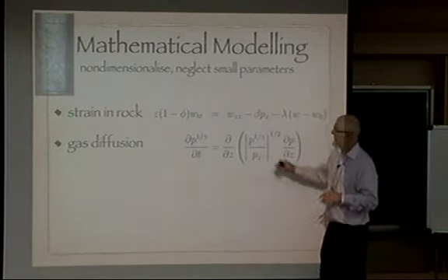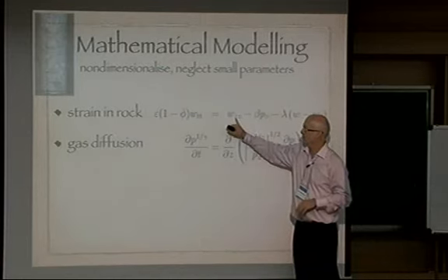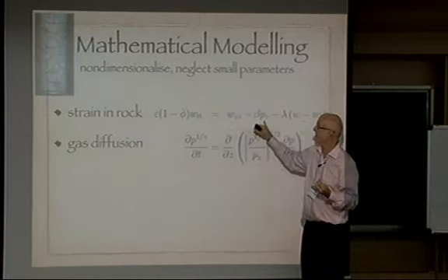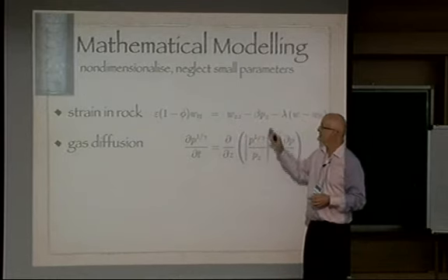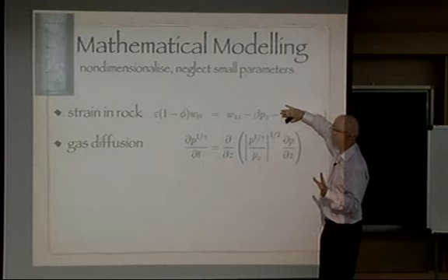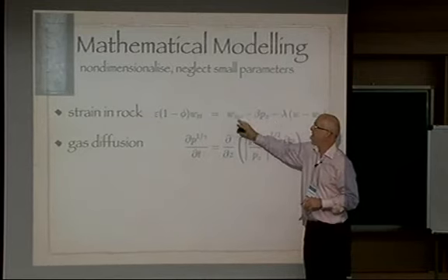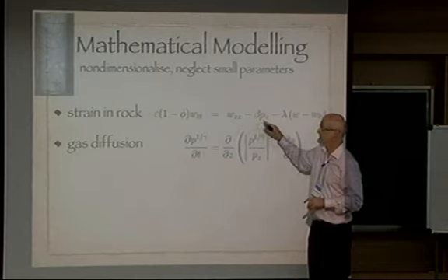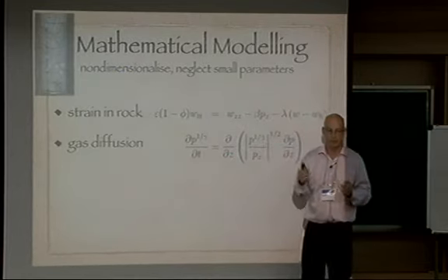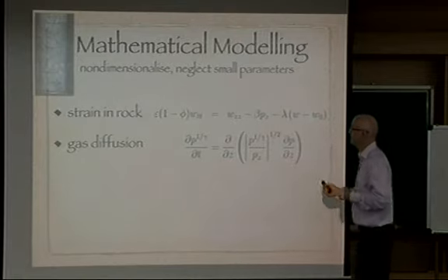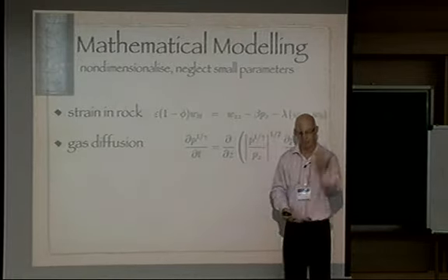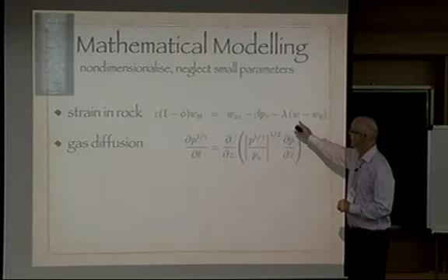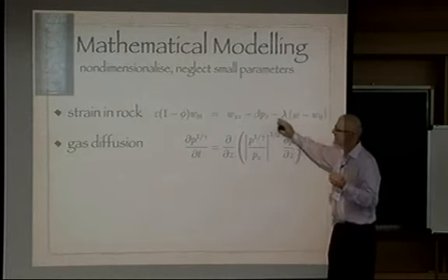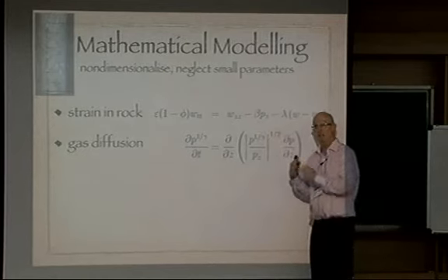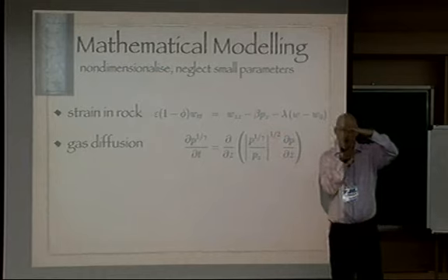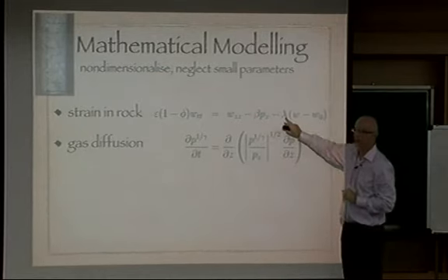I should be a bit more careful about saying that. I want to get W subscript Z, dW dz, that's the stress. So I integrate this and I get pressure. The pressure curve to leading order, if lambda is small, if there's no glue, for example, the pressure gives you the stress, just the pressure. Changes in pressure are changes in stress. The maximum pressure is at the bottom, so it predicts lift off from the bottom, always. But with the lambda in there, that modifies it slightly, just enough to give a maximum pressure nearer the top of the sample. So that was the magic ingredient in the modelling.